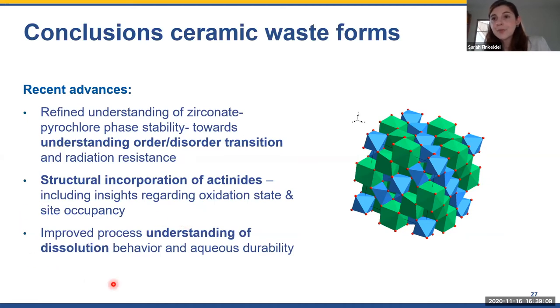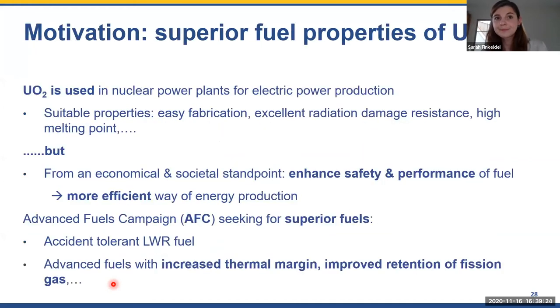And we also could develop an improved understanding of the dissolution behavior. So not only rates, but we could also understand that the dissolution actually happens by dissolution of the grains themselves, and that grain boundary dissolution is not the main mechanism.